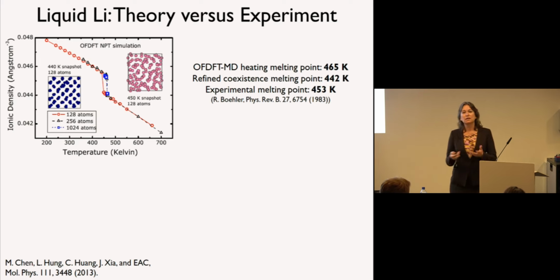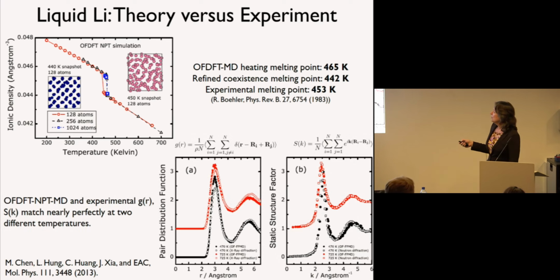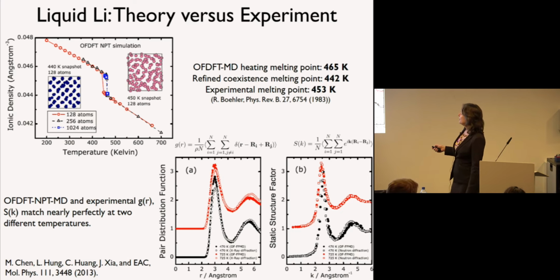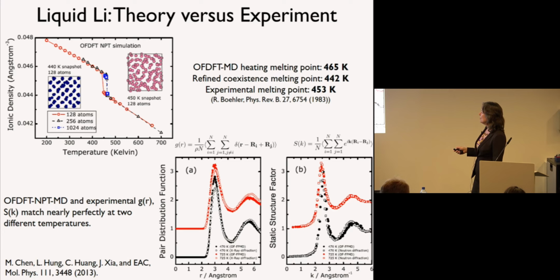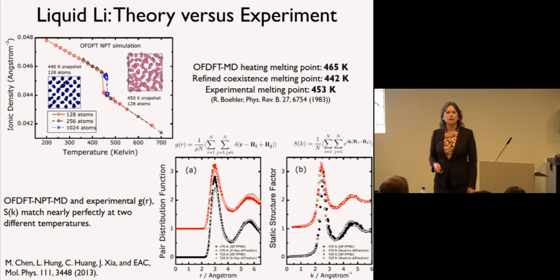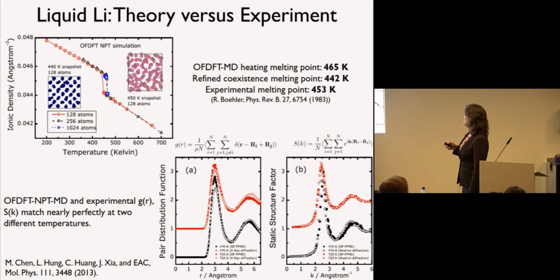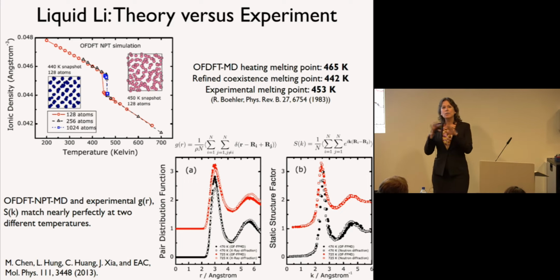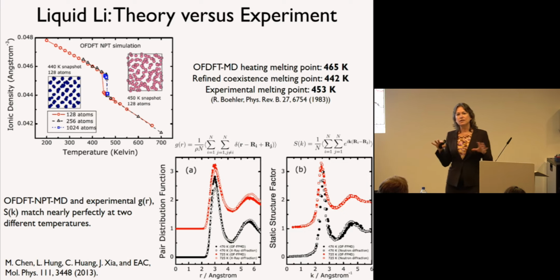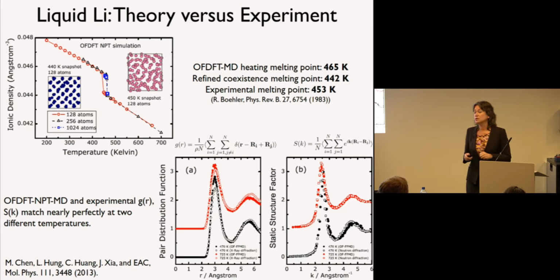So we can really describe lithium very well with orbital-free density functional theory, both in terms of the melting point, but also in terms of both the pair distribution function as well as the structure factor. The solid is our orbital-free density functional theory results, and the open circles are experiments, X-ray diffraction and neutron diffraction. The black is low temperature and red is high temperature, and they look very good. So liquid lithium is well described. This is not surprising because we can do very well at describing nearly free electron-like metals with our kinetic energy functionals that are based on linear response theory, using the Lindhard response as a way of being able to describe it properly.